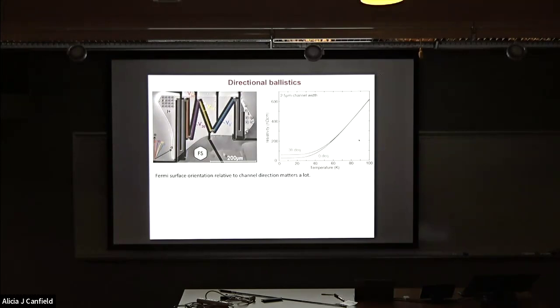So there's one meander track, the current's going all the way through that meander, but we have the legs of the meander at different angles. And the two extreme angles in hexagonal symmetry would be 30 degrees and 0 degrees. And you can see that up at 100 Kelvin, when your scattering length is shorter than any characteristic size scale of the device, you're isotropic, as you should be for a triangular lattice. But then when you get down below that, you develop quite a pronounced anisotropy. And this is early work. We can make the anisotropies up to about a factor of 5 now between the easy and the hard direction of transport. So this is a cool effect, but we didn't take it into account when analyzing the 2016 experiment.